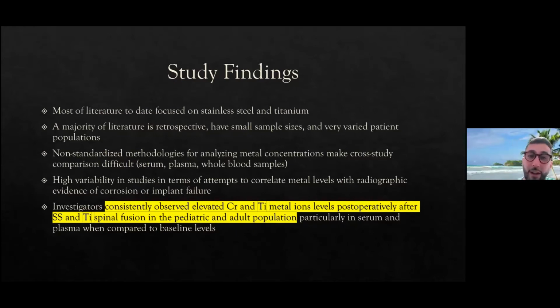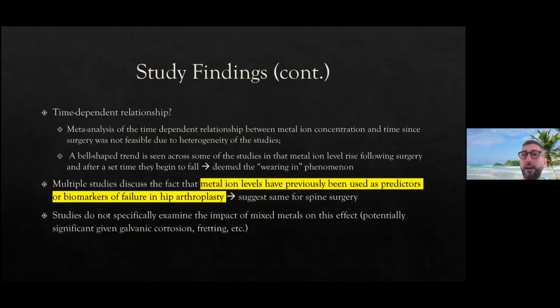Additionally, there's high variability in their attempt to correlate the metal levels with radiographic evidence of corrosion. Having said all that, there were some interesting things, mainly that they observed elevated levels of chromium and titanium ions postoperatively after stainless steel and titanium fusion. And that was particularly true in the plasma. There's also this time-dependent relationship, which I think is kind of self-evident, but basically you see this bell-shaped curve. You see a rise in the ion levels immediately after surgery, which makes sense, right? Because we've been manipulating that hardware in the body, and over time, those levels seem to fall, and they call that the wearing-in phenomenon.